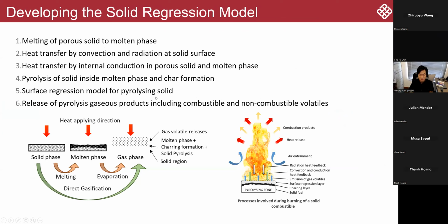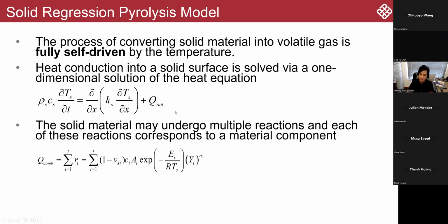And once we use that, we can utilize this technique for both MD or TGA data, and we can extract useful information for CFD modeling to describe the pyrolysis process. But MD gives us an additional result on the gas volatile, so we can even identify the primary gas that is flammable in the combustion process, which is very important.